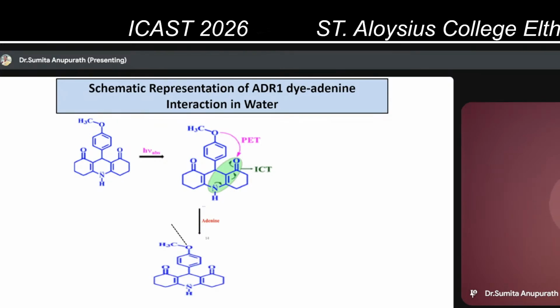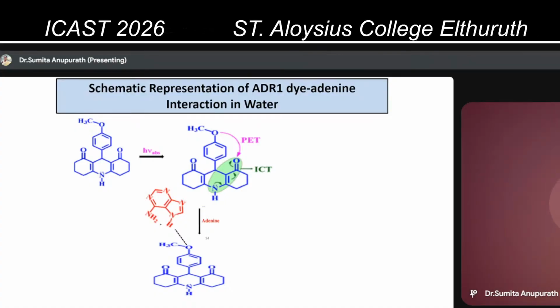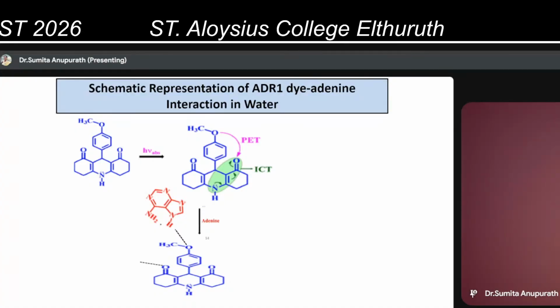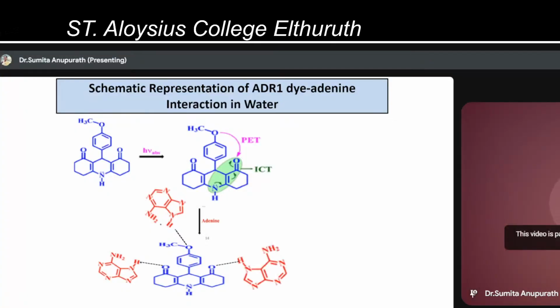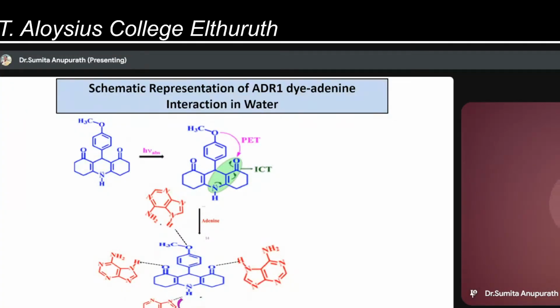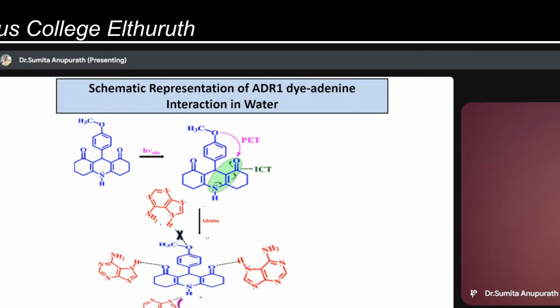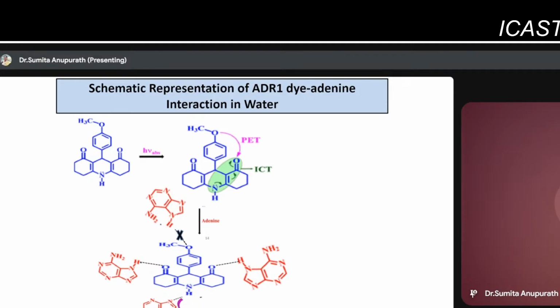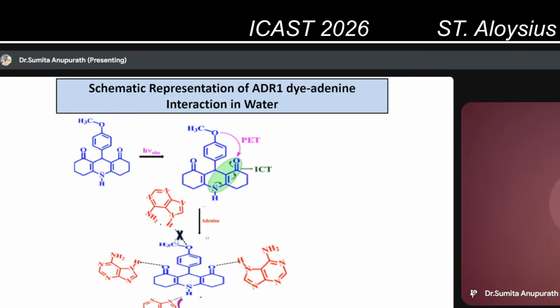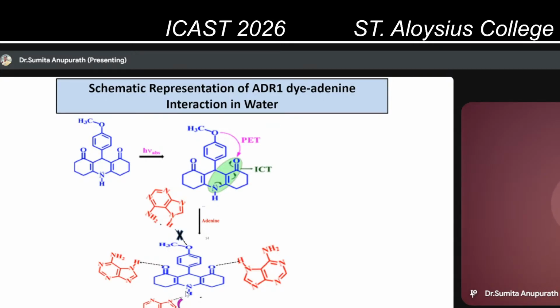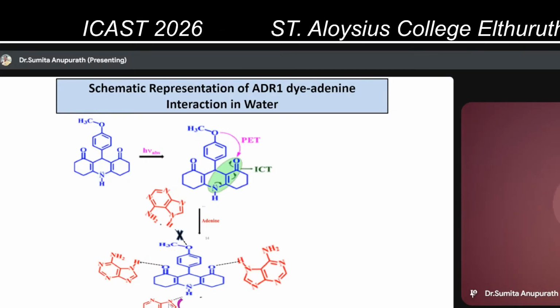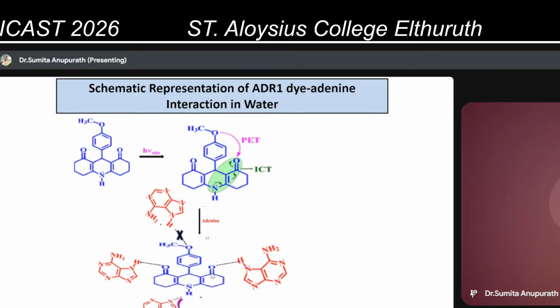It can bind with the methoxy oxygen. It can bind with the carbonyl oxygen. It can bind at the NH position. But it has been shown by quantum mechanical studies or energy minimization studies that the adenine does not prefer to bind at the methoxy oxygen. That has been established by the quantum mechanical studies. Rather, it prefers to bind through hydrogen bonding to the NH group or the carbonyl oxygen.